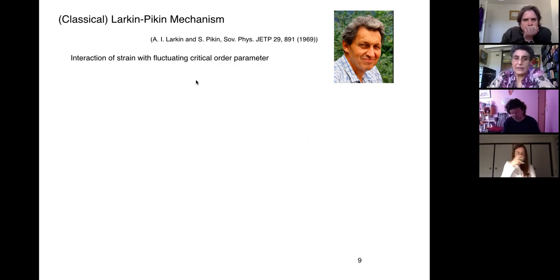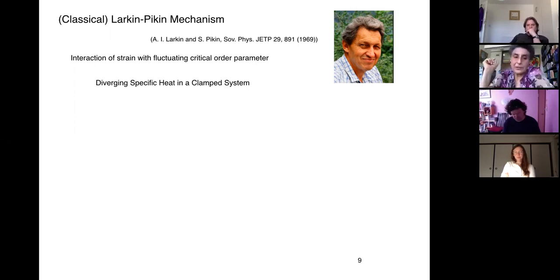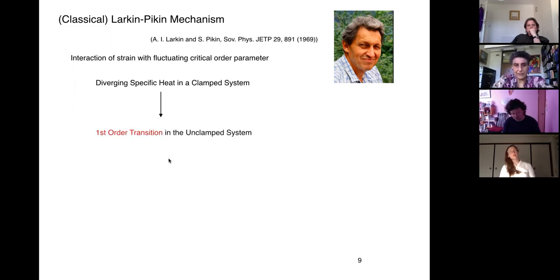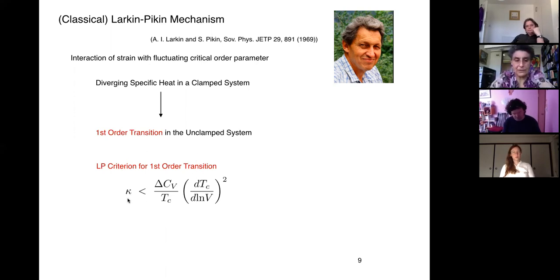So what Larkin and Pikin did was they had a strain energy density coupling. They took a compressible system that had a divergence of the specific heat in a clamped system. So you clamp the system, that is, you have no volume change, and you have a well-defined second order transition with a diverging specific heat. Then you unclamp it, and when you unclamp it, you get a first order transition. Okay? So the Larkin-Pikin criterion for this first order transition is that kappa, the effective bulk modulus, is less than the specific heat over temperature times the square of the change in the transition temperature with strain.